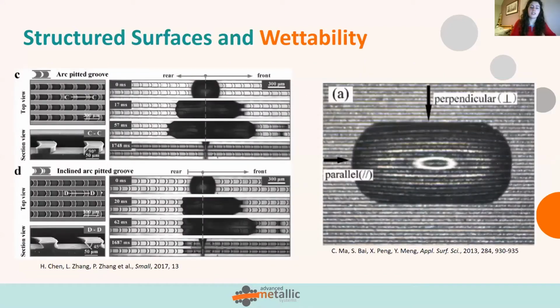This is just a larger version of the image that was on the previous slide. Between the top and bottom results, the only change is from the straight groove down to an angled groove at 45 degrees. The very bottom right of the first image shows the extreme preference for moving the water in a forward direction, and it pins the backward direction because it's controlled by capillary action.